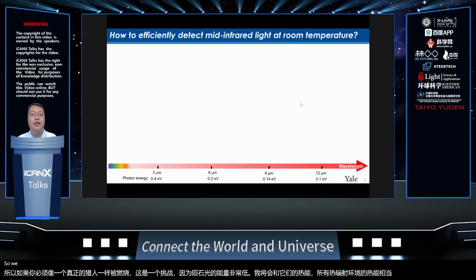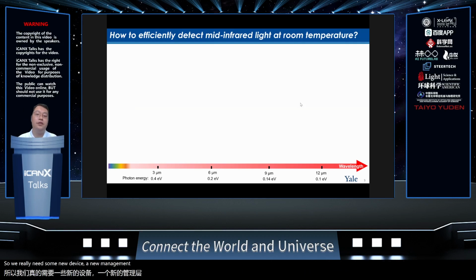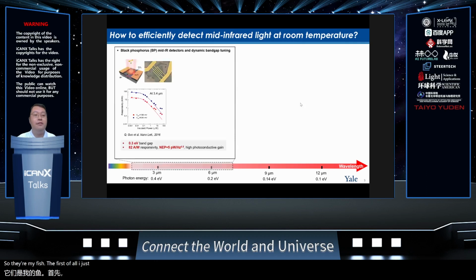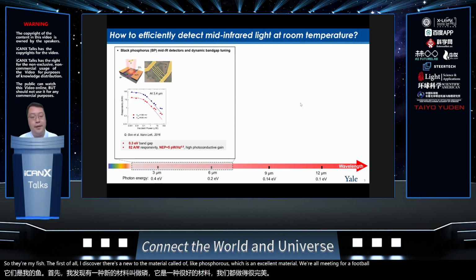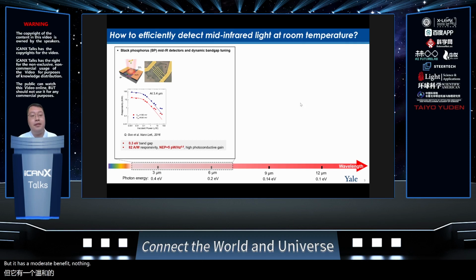So we really need some new devices and new mechanisms to tackle this challenge. During my PhD, first of all, I discovered a new 2D material called black phosphorus, which is an excellent material for mid-infrared photonics. It has a moderate band gap of 0.3 eV. By using this material, I demonstrated the first black phosphorus mid-infrared detector in the world, which offers a very high responsivity, high photoconductive gain, and a very low detection limit of 5 picowatt.